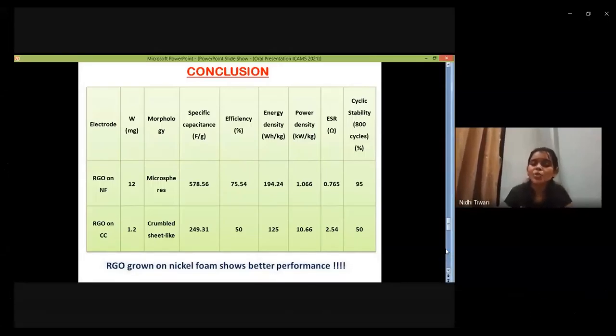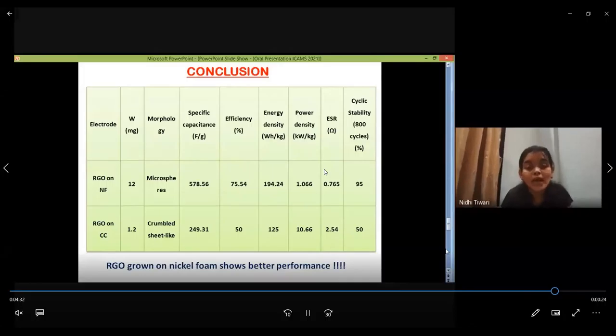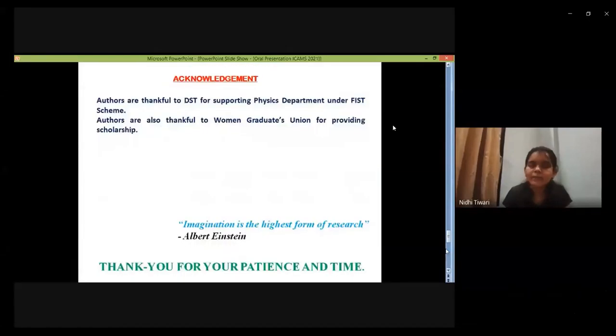So from this, I can conclude that RGO grown on nickel foam might show better performance as compared to RGO grown on carbon cloth in 1 molar KOH. So KOH supports nickel foam performance, but it does not support performance on carbon cloth to that extent. So this was all about the studies which we have completed.